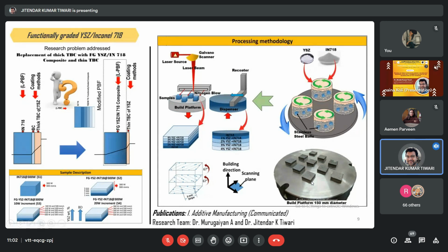Okay, and this BC is the bond coat. This bond coat is basically used to address the thermal mismatch between these two materials. Why do we have thermal mismatch here? That is a very important question to understand. This particular material has a different thermal expansion coefficient, and this material has a different thermal expansion coefficient. When we increase the temperature, this will expand a lot, but this will not expand at the rate this particular material is expanding. So obviously it will crack.